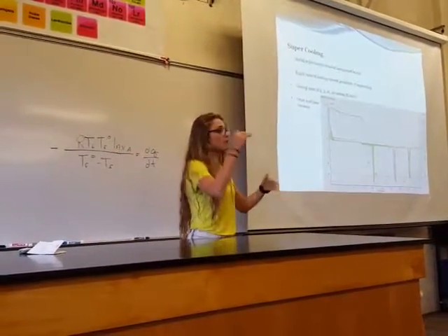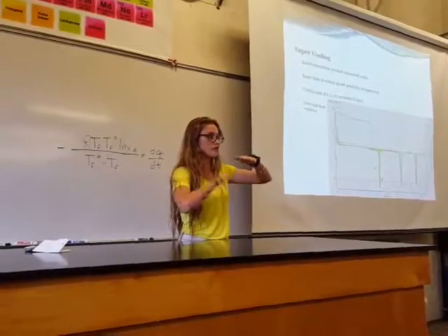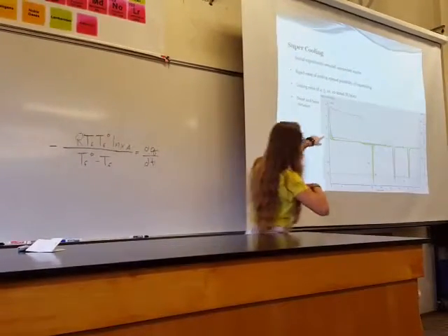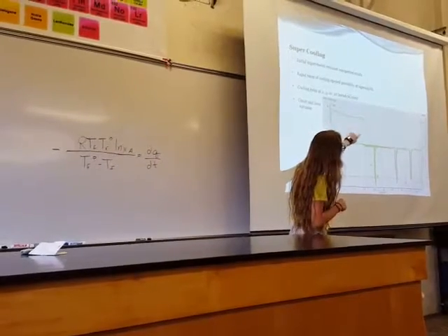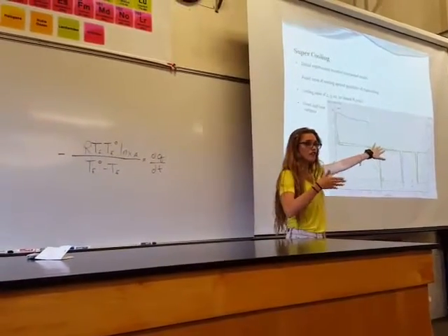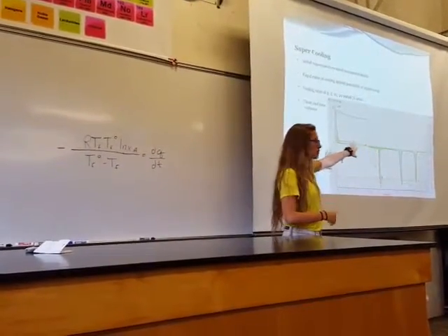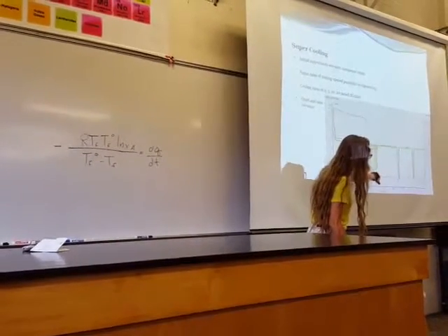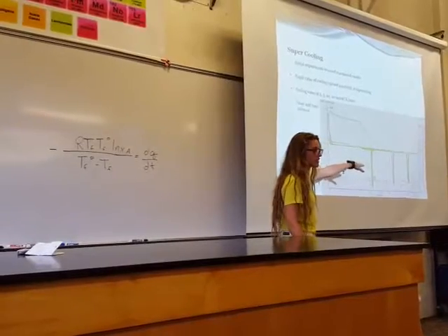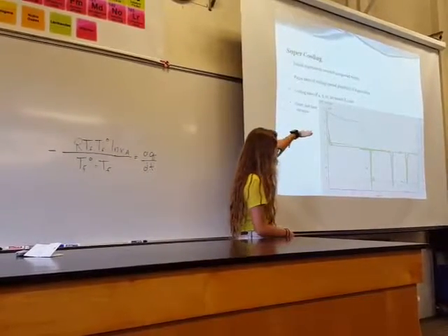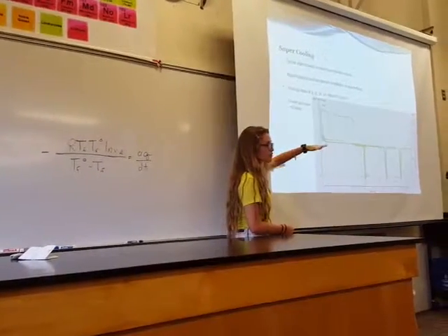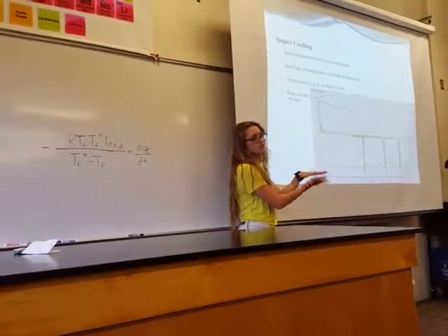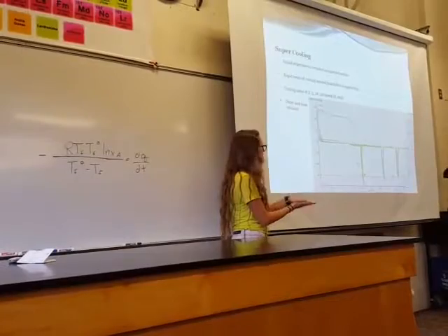And what happens is it goes below freezing temperature, so water freezes at 0 degrees. However, when we were rechecking and trying to understand why the results weren't what we expected, we found that as we froze it at different rates of cooling in kelvins per minute, the freezing temperature would not be at 0 degrees Celsius, but instead it was at negative 14 degrees Celsius to negative 20 degrees Celsius.